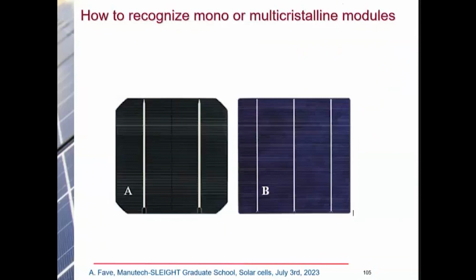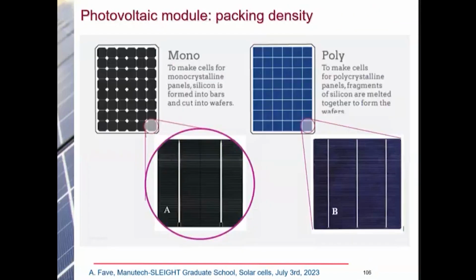So you have these two kinds of solar cells. This one is single crystal and multicrystalline solar cell. When you have a very efficient texturation step, it's very difficult to recognize multicrystalline solar cell. You almost cannot see the grain, but the difference between these two is here. It's coming from the fact that the single crystal is a circular wafer. So you cut it like this to have high density of material on the module. Meanwhile, for multicrystalline, it's easier. You just put the square in the module.